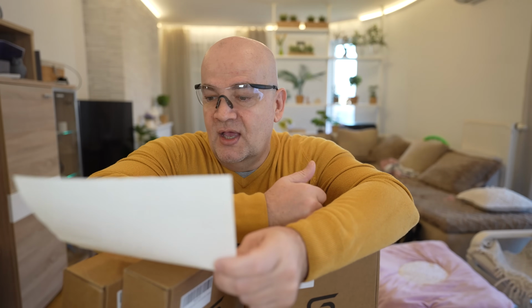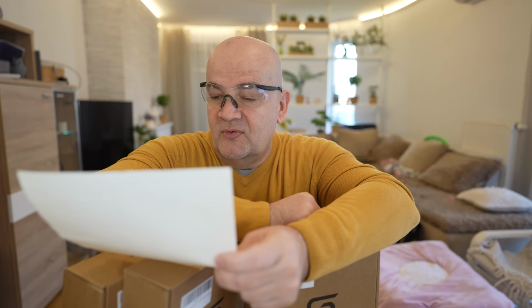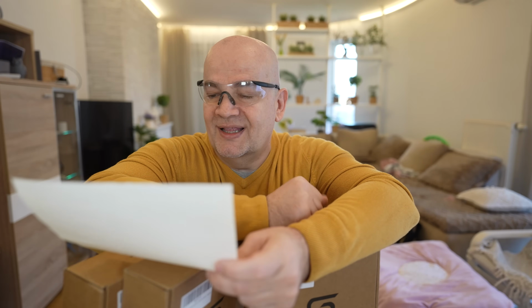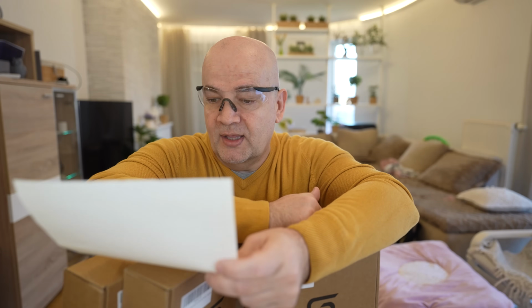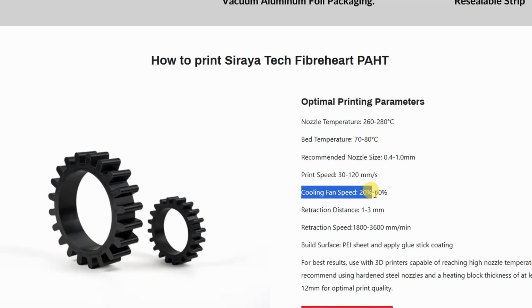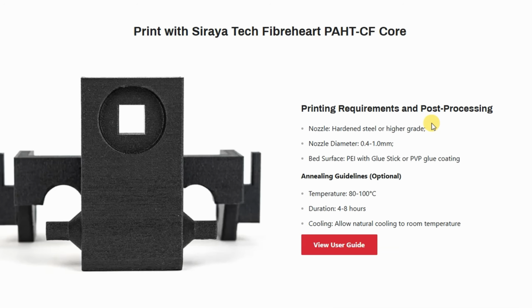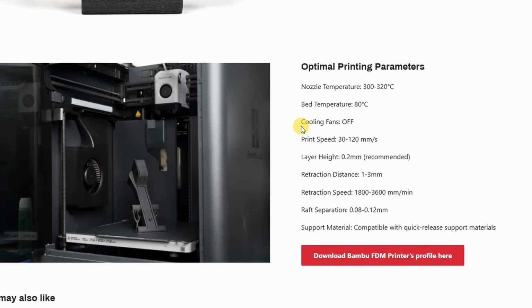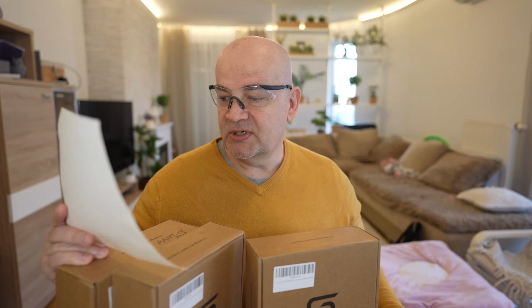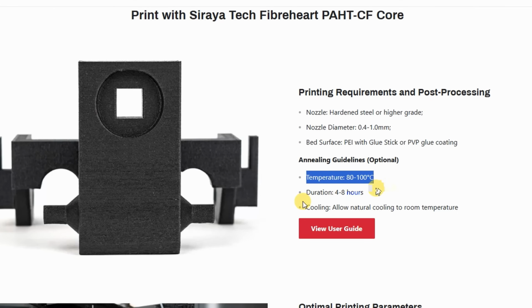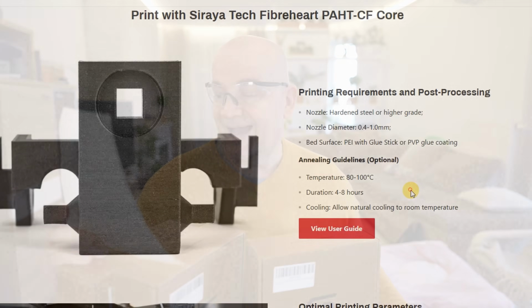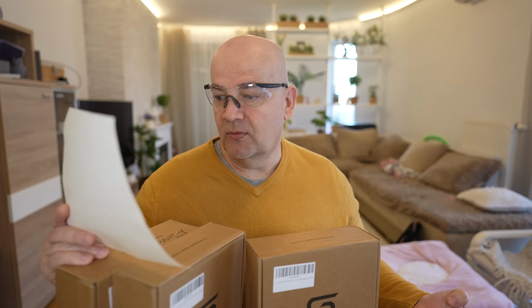And I want to do this printing on X1 Carbon, so the maximal temperature here is 300 degrees Celsius, which will be my setting. Print speed up to 120 millimeters per second, and I calculated it is approximately 10 cubic millimeters per second flow rate. Cooling fan speed between 20 and 60% for the regular version, and for the carbon fiber version it can be switched off. About annealing, the temperature between 80 and 100 degrees Celsius and the time between 4 and 8 hours, and at the end slow cooling.